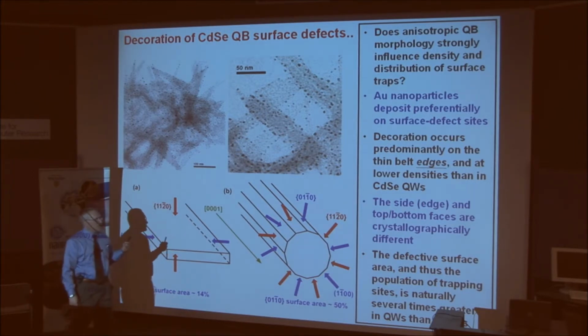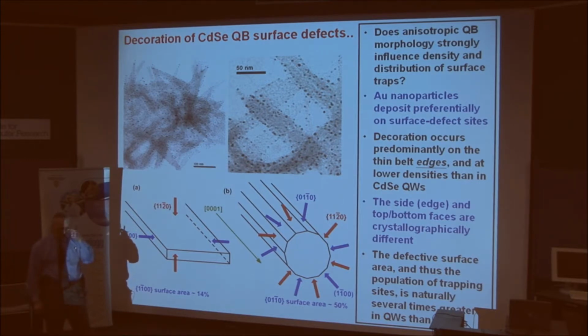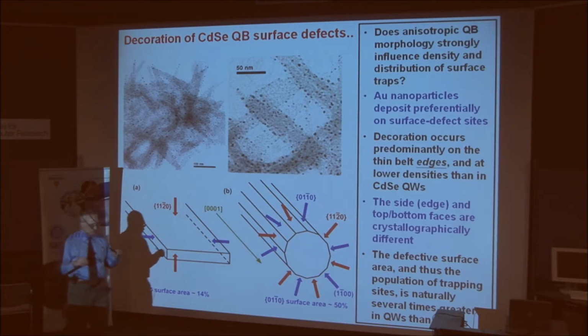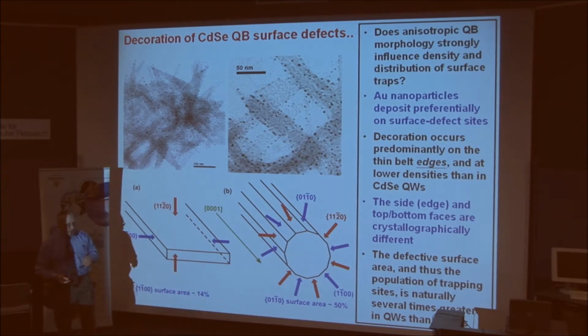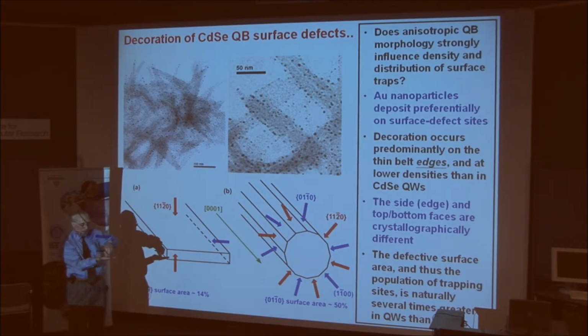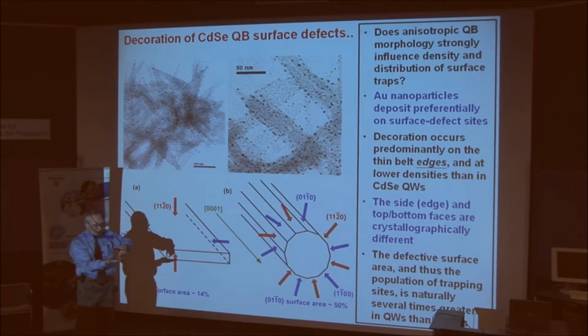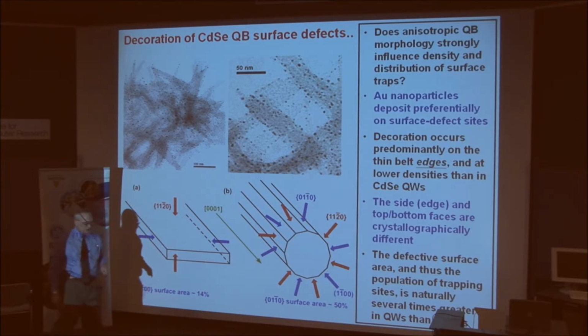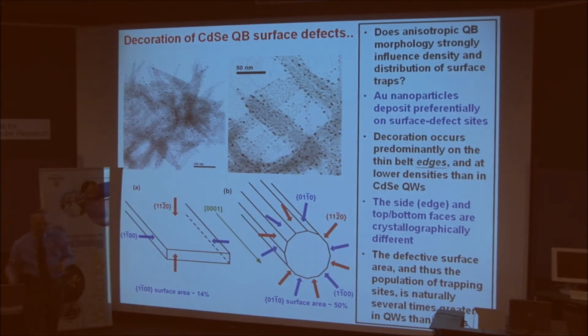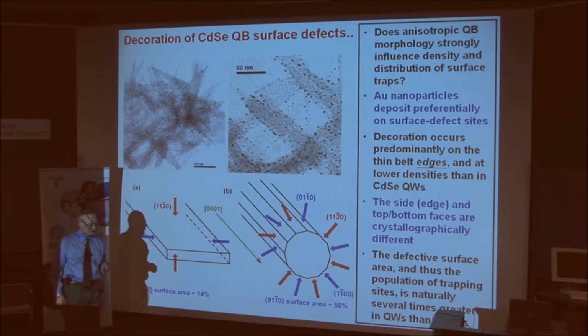And the first time that a decoration strategy like this was used in science and engineering, to my knowledge, was in the 1930s, when the goal was to identify the microscopic surface cracks on glass. And this is at a time when there was no electron microscopy, and these cracks were so small you can't see them with an optical microscope. And so you take a piece of glass and you expose it to mercury vapor. And the mercury vapor cools and condenses on the surface of the glass, but it nucleates particles preferentially on the defect sites on the glass. And so if this experiment is done carefully, one can actually decorate the surface cracks, count their density, and relate that density to the strength of the glass. This kind of strategy was later used to identify the emergence of dislocations from crystals in the 1950s.